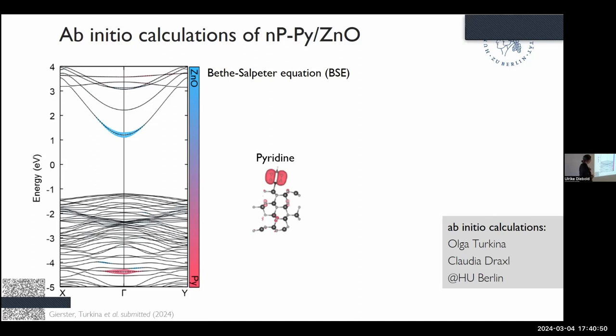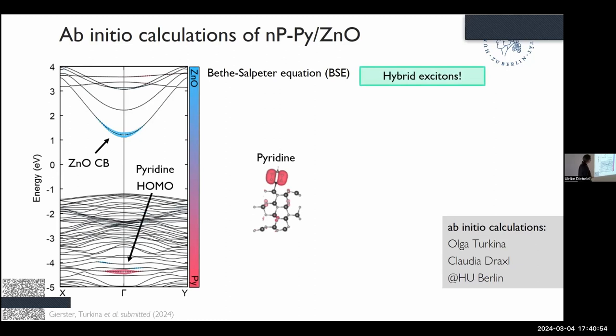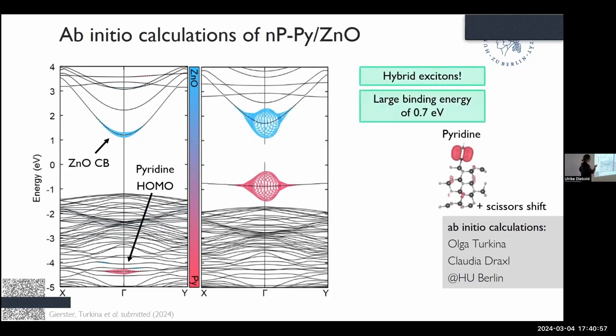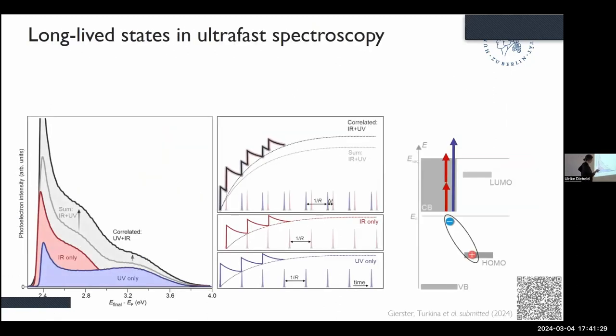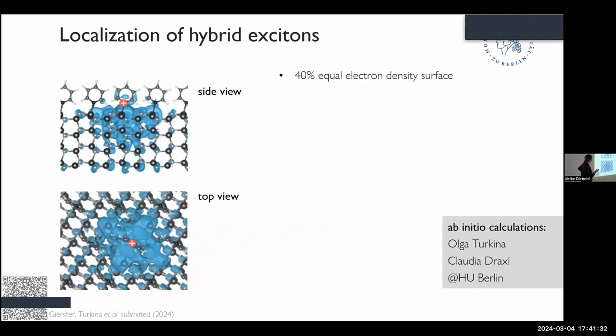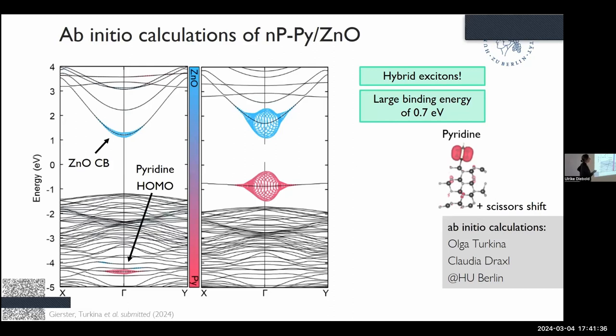So what we did was we took the experimental values for the LUMO and the optical gap, and then we shifted the HOMO into the band gap, into its position. And this shows that, because we do not have this hybridization with all the valence band states, we have a very strong localization of holes on the molecule while the electron is sitting in the zinc oxide. And these hybrid excitons actually have a very large binding energy of 700 millielectron volts. That's gigantic for such a system.